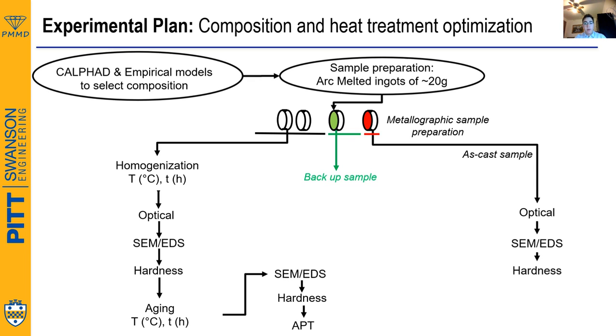Selecting a pair of the best composition candidates, we cast 20 gram ingots via arc melting. Based on the microstructure predictions obtained by CALPHAD and in-house developed models, we came up with both the homogenization and aging temperatures as well as the aging times for the study, to study the full picture of the aging evolution.